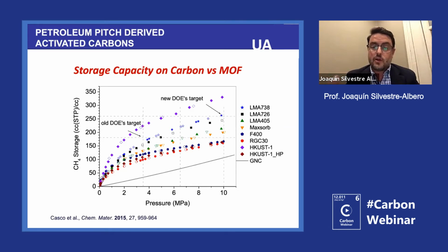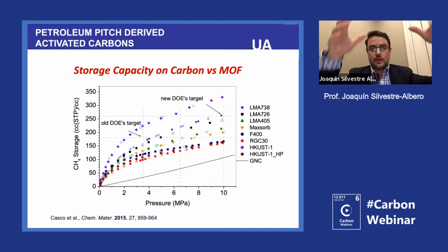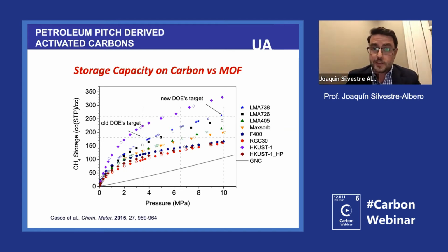So that means that compared to this specific MOF, in the case of the carbon you have a higher mechanical stability. Another important thing is that these calculations with MOFs are done with the theoretical crystallographic density. So this assumes that we have a perfect crystal, and we know that this is not true. I mean, these measurements were done with a powder, which is really far away from a real crystal. So at least the message is that carbon materials can compete with MOFs, and somehow we have certain advantages in terms of mechanical stability and other properties.